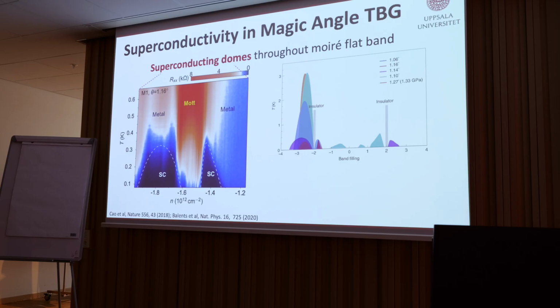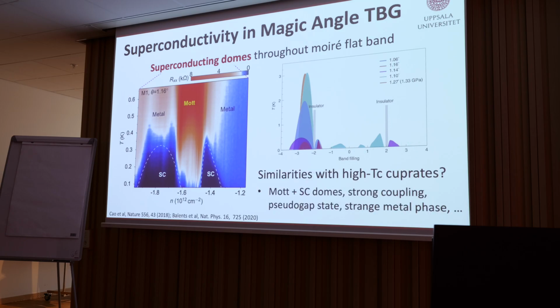So it's not just around plus or minus 2, even though there you have the highest. This is different experiments at different angles, measuring Tc for superconducting domes. You see there's a lot of superconductivity here, but essentially throughout the band filling of the Moiré spectrum, you do seem to have small domes of superconductivity.